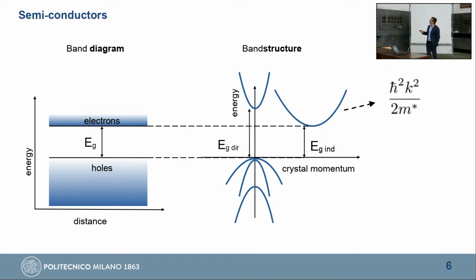This band structure, we will see later some more realistic representation, can very often be approximated using this parabolic behavior. So we fit a parabola around the minima or maxima of the state, and this parabola will describe the motion of a particle with a mass which is no longer the electron mass, but the effective mass, where essentially this number here, actually in more complicated vision is a tensor, but say this number is actually condensing all the complexity of the band structure.